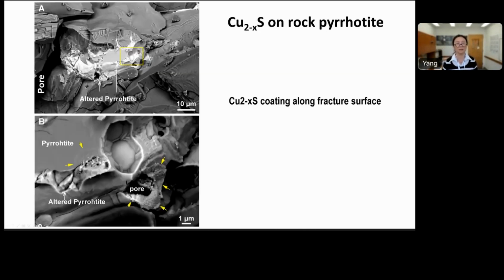So here is a zoomed in image of that region. Over here is a continued zooming in image of that pyrrhotite grain inside the rock matrix. This is a fractured surface. So we got the chip as is, and this is on the surface that was chipped off. On the surface of the fractured plane, we see a copper sulfide again, coatings along those fractured surfaces.